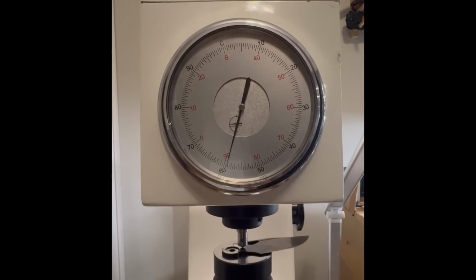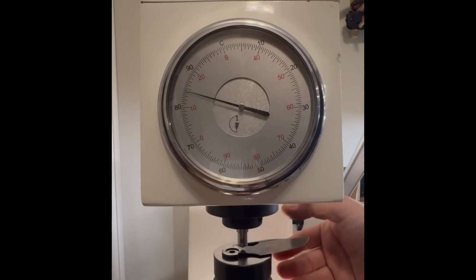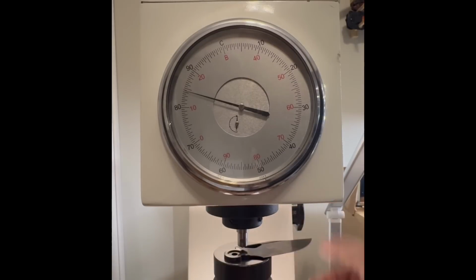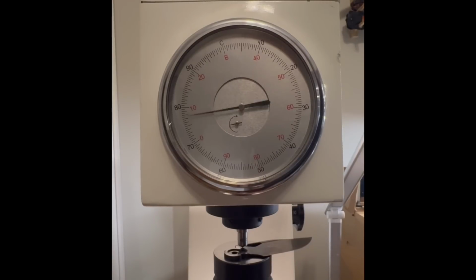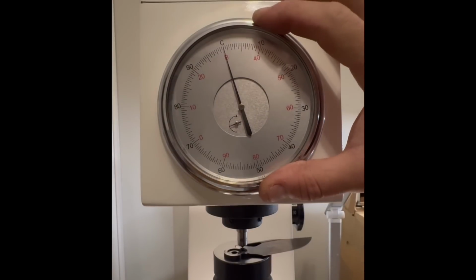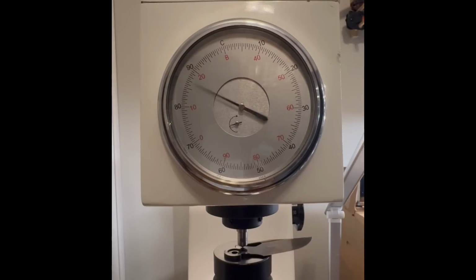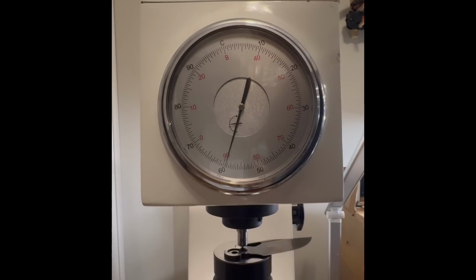59.3. Oh, did I mention I am testing on the coated part of the blade that still has coating on it? My prediction is it's not going to affect the hardness, because then I will test on the exposed parts where the metal is already exposed, coating removed. And I got 59.5.